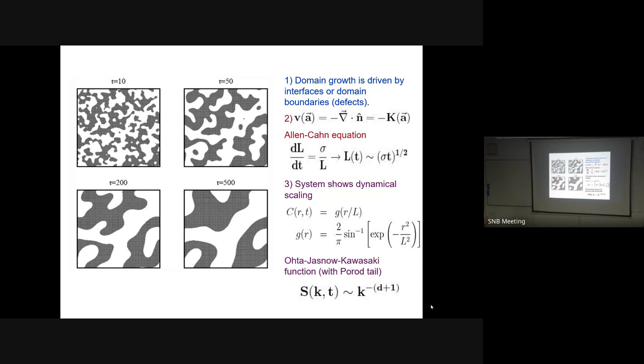By simple dimensional analysis, if the length scale is L(t), the velocity of the interfaces is dL/dt and the curvature is 1/L. Integrating this up, you get the first non-trivial result: the length scale grows as the square root of time, L ~ t^(1/2). The scale is set by the surface tension, which is what drives the system.